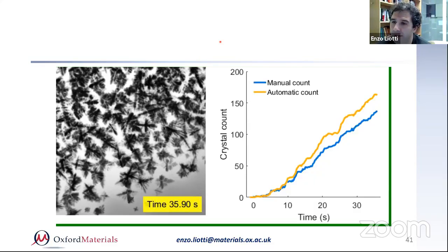If the oxide has a different composition than the metal, in particular in terms of density, then you will be able to detect it. The fact is that in our sample, there is always a film forming on the surface, right? That generally is too thin to be detected. If you have a 200 micron thick sample and your layer is 1 micron, then there is not really a chance that you can distinguish it. But we had an experiment which used another type of contrast. We were able to look at the surface, so you can detect it. In terms of inclusions, if you have particles or intermetallics, then you will see them.